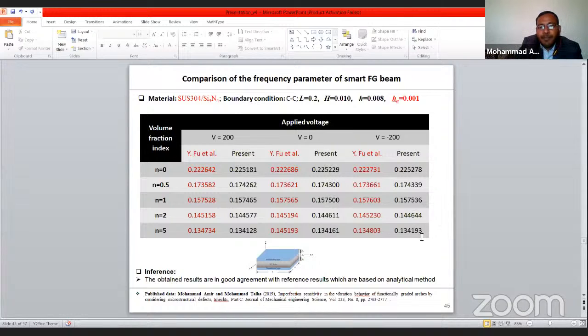And here a comparison is presented for the smart functionally graded beam. For the comparison purpose, I have considered a straight beam where we kept the radius of curvature equal to infinity, as well as the thickness of the piezoelectric layer is 0.001 meter. We applied the voltage potential difference, 200 volt, 0 volt and minus 200 volt, and we compared our result with the existing results for various volume fraction index. So we found there is a good agreement between the results.